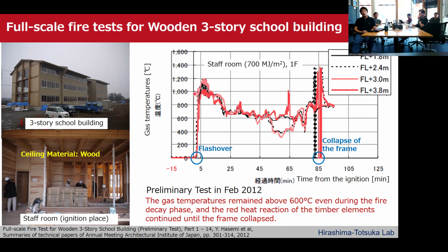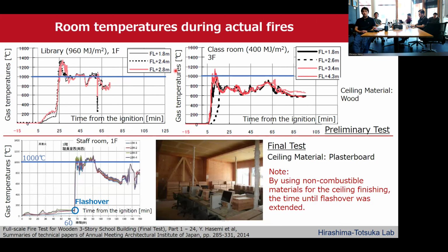The room temperature quickly reached 1,000 degrees. The room temperature remained above 600 degrees even during the fire decay phase. And the red heat reaction of the timber elements continued until the frame collapsed. So the top two graphs show the temperatures in the other rooms in this test. The blue line is 1,000 degrees. High temperature continued in other rooms during the fire decay phase.